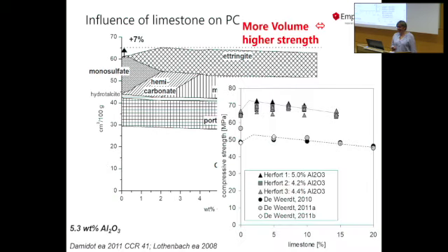But maybe much more important for you: if you have an old cement which does not yet contain any limestone and add a bit of limestone to it, you in fact can see a maximum at around 2 or 3% limestone and then going down. And the other cool thing is that up to 10 or 15% replacement, you will have the same compressive strength as an old Portland cement which did not contain any limestone. I must say, industry figured that out before we understood what happened, because this was introduced maybe 20 years ago. But the understanding also helped us figure out what was going on, and it's also the foundation for the development of more blended systems like Portland limestone calcined clay cement. Because when you understand that you make more and more ettringite, you can play with it.